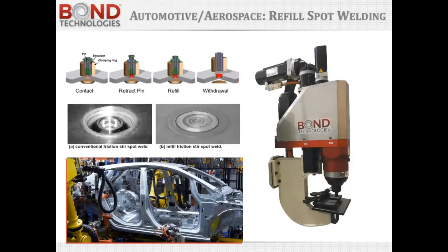Another growth opportunity for friction stir welding is a variant called refill spot welding, or friction stir refill spot welding. This is a process that can be used to either replace conventional resistance spot welding for aluminum or self-piercing rivets. There are 4 steps to the process. One is that picture, if you will, a shoulder and a pin or a probe. So they're concentric rings, and on the outside of those is a clamping ring. So in initial contact, the clamping ring, the probe, and the shoulder are all flush with the surface of the part. The clamping ring is not rotating, but the shoulder and the probe are rotating.